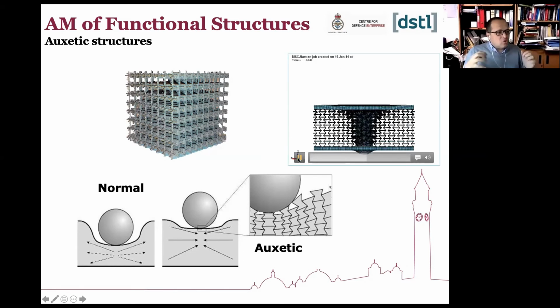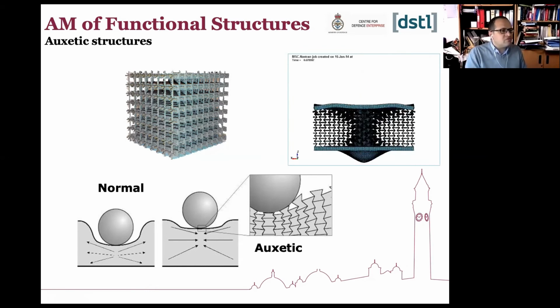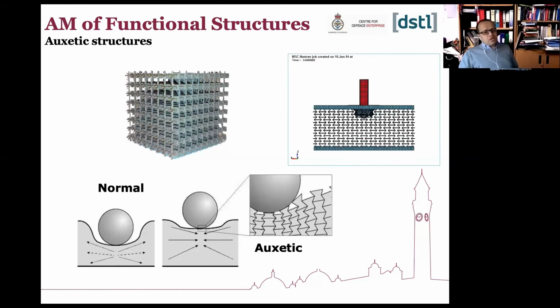Basically, the material will move towards blocking it and it will densify to prevent it from further progressing inside the material. So this is where, if you want to think about it, if you put the same amount of material as a simple block compared with putting the same amount of material but only as an auxetic shape, you will achieve a much more significant behavior from an armor point of view, and the prevention of the material progression when it's hit during impact. Talking more about topology and how topology can be interestingly computed and controlled.